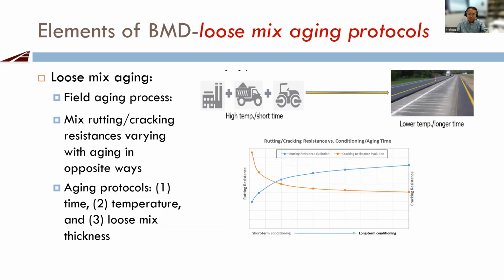For the rutting resistance, like this blue line, it's getting better and better. And for the cracking resistance, this orange line is getting worse and worse. So that's why for rutting, short-term aging is critical. For cracking, long-term aging is critical. So we have to consider both short-term and long-term. So in terms of the aging protocol, we have to consider how long we're going to age the loose mix in the oven, what temperature we should use, and how thick our loose mix should be.